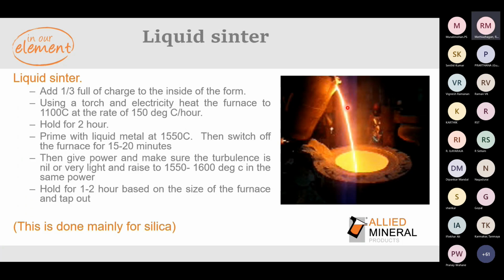When it comes to liquid sintering, this is one of the best sintering practices, but many people are concerned about engaging this in their operations. But it's very safe if you do it in a proper manner, and it gives a longer lining life for your refractories. We recommend loading 1/3 of clean scrap inside the form with the help of a gas torch. Raise the temperature to 1100 degrees Celsius at a rate of 150 degrees Celsius per hour. Hold the furnace for 2 hours.